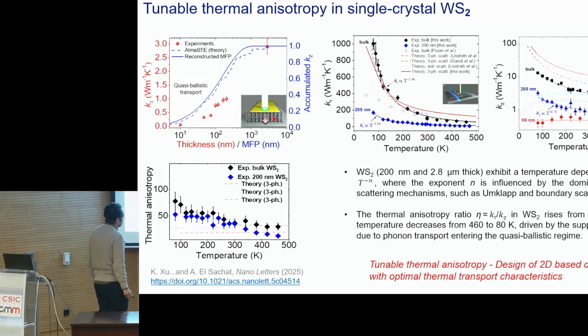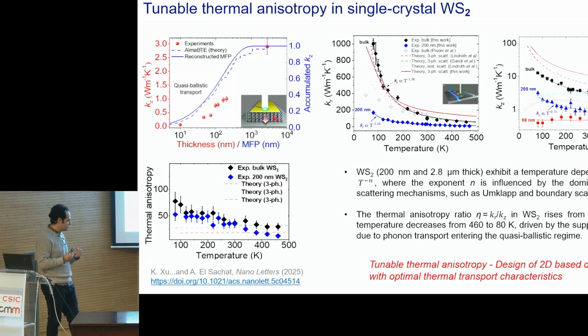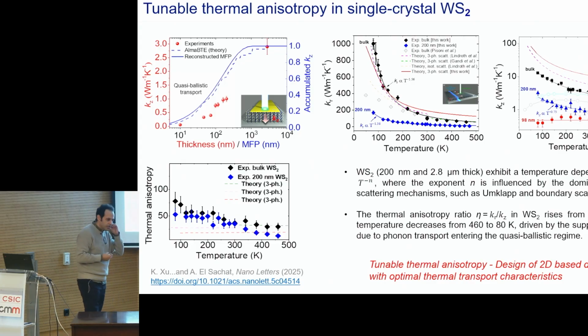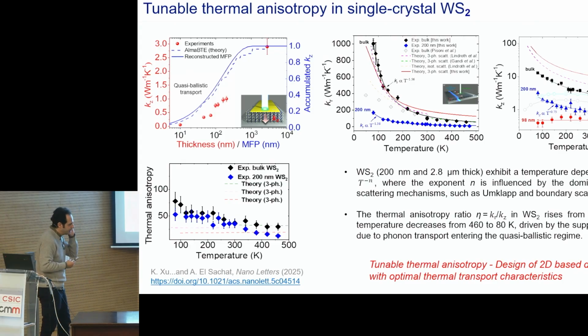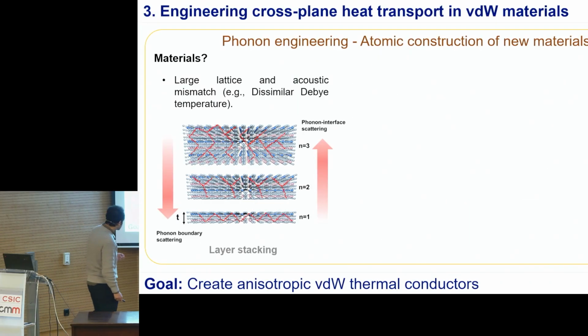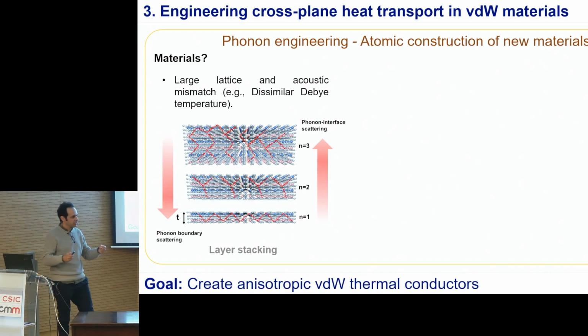as a function of the thickness and the temperature, from which we can extract directly the thermal anisotropy in our material. So you see that the thermal anisotropy can be tuned, depending on the temperature that we are using or the thickness, which is quite useful if we want to design a new device from the beginning. So we really need to know the thermal transport characteristics of the 2D semiconductors that we are using. Okay, so we saw how we tune the in-plane thermal conductivity. We saw how we can measure the thermal anisotropy, and let's see what about the cross-plane thermal conductivity. So for this, we are using superlattices. We are using layer stacking, either by exfoliation or by growing using epitaxial methods.